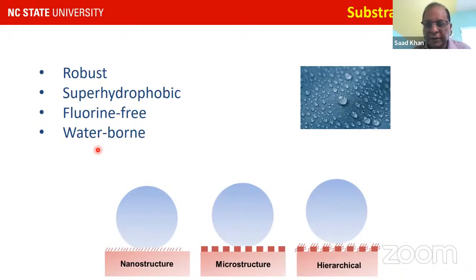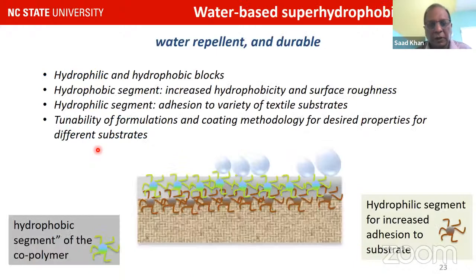And we played around, and the approach we took is a block copolymer approach. So the idea would be that we would have block copolymers of hydrophilic and hydrophobic moieties. The hydrophobic segments would add to the surface roughness and the hydrophobicity. The hydrophilic segment would provide some adhesion to the textile substrates, and presumably by changing the amount of hydrophobic and hydrophilic components, we can create formulations with the best of both worlds, or we can do maybe multiple coatings and so forth. So that's the approach we took, and that's what I'm going to share some of the results with in the next few minutes.